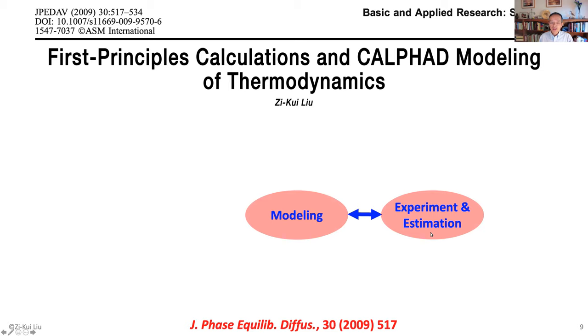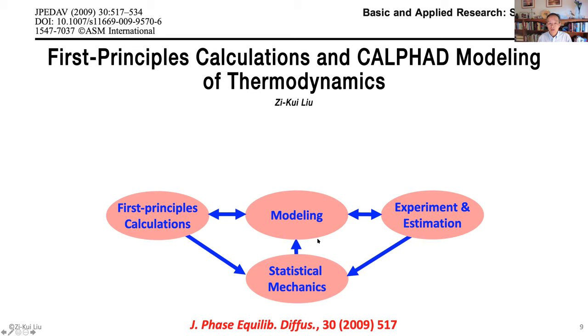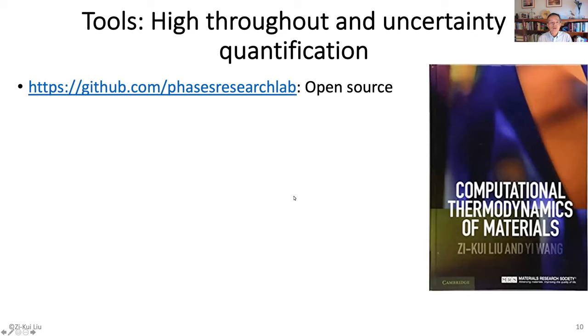About 20 to 25 years ago, most CALPHAD modeling was based on experiments and estimations. Then first-principles calculations became a very powerful tool, mostly for zero Kelvin. Now with statistical mechanics you can include finite temperature. So we take experimental data and first-principles data together, which makes predictions much better and CALPHAD databases much better. The predictive power is enhanced. Our group has been focused on developing high-throughput open-source codes with uncertainty quantification capability.